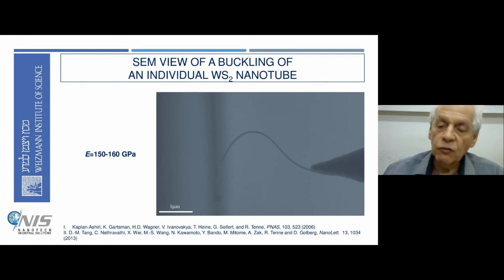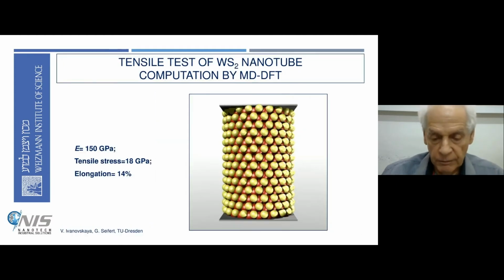You see how the nanotube is flexible and does not break. If I stick this nanotube to a tip in the microscope and she compresses it against a silicon wafer or some other surface, she gets this beautiful folding of the nanotube. So the nanotube is not breaking, it's folding. This is a very important finding, because now we see we have a material which is both very strong and very flexible. This is quite unique, as you'll see in a minute.